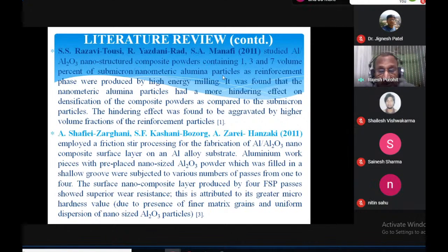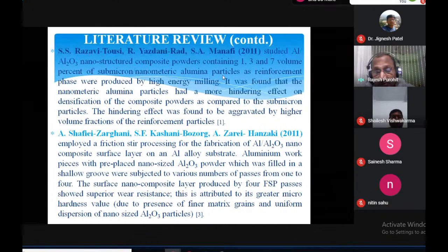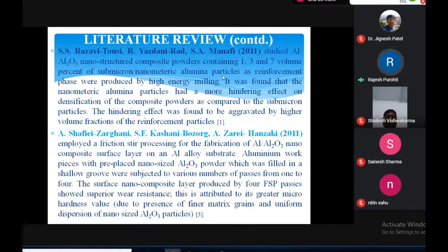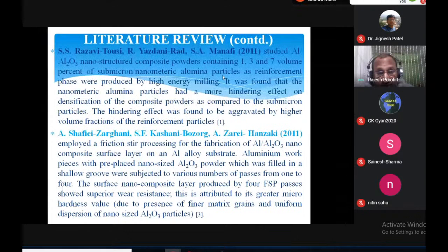Then coming to some other literature. Like S. S. Rajvi has studied aluminum oxide nanostructure composite powders containing 1, 3, and 7 volume percent of submicron and nanometric alumina particles as reinforcement phase, produced by high energy milling. It was found that the nanometric alumina particles had a more hindering effect on the densification of the composite powder as compared to the submicron particles. The hindering effect was found to be aggravated by a higher volume fraction of the reinforcing particles.